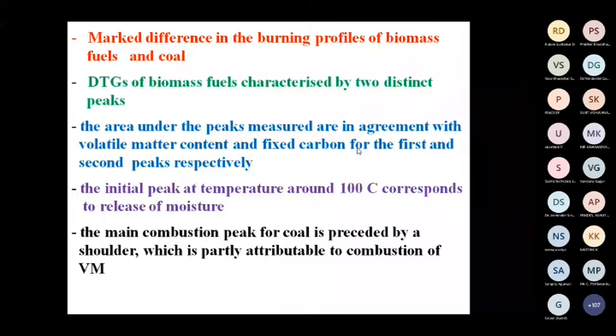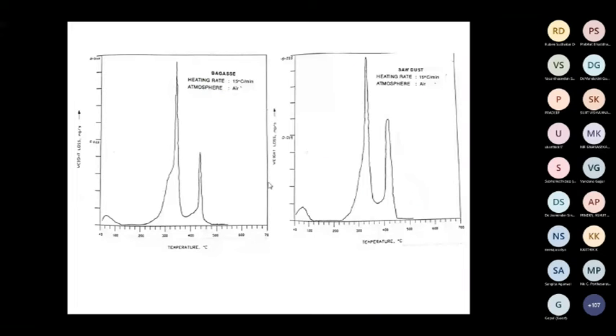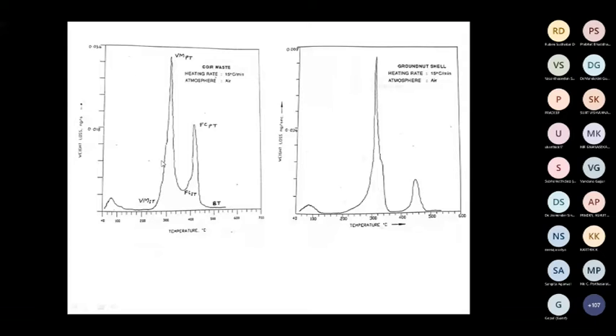What is the difference? All the DTG curves of the biomass fuels are characterized by two distinct peaks. The areas under the peaks are in agreement with the first peak being for the volatile matter content and fixed carbon in the second peak. So the initial peak at around 100 degrees corresponds to release of moisture. So now you see, this is the release of moisture. This peak is related to combustion of volatile matter. This peak is related to combustion of fixed carbon.